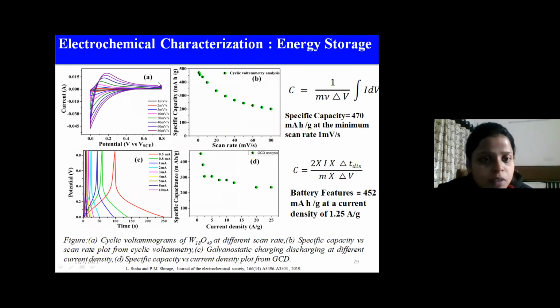And from cyclic voltammetry, we are seeing that the material is giving a pseudocapacitor nature by showing the redox peak of oxidation peak at 0.18 volt. And here we have calculated the specific capacitance, which is 470 milliampere hour per gram at a minimum scan rate of 1 millivolt per second.